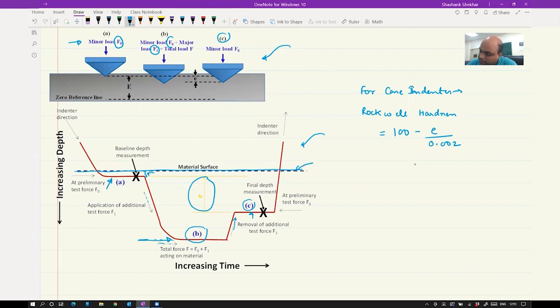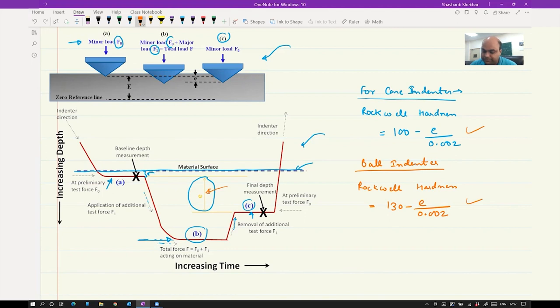And if we are using a ball indenter, the Rockwell hardness will be 130 minus E divided by 0.002. So depending upon whether your indenter is a diamond cone or a ball, you use two different formulas like this, depending on the value of E. And again, the Rockwell tester gives you the values automatically.